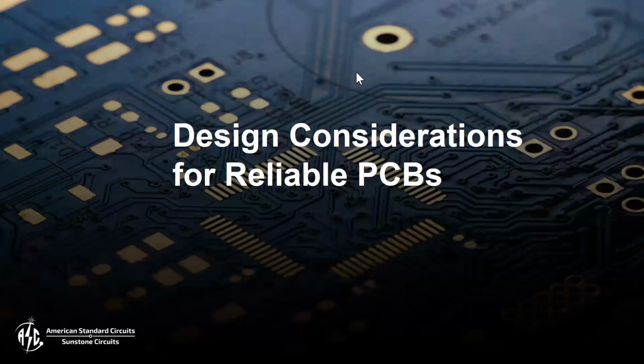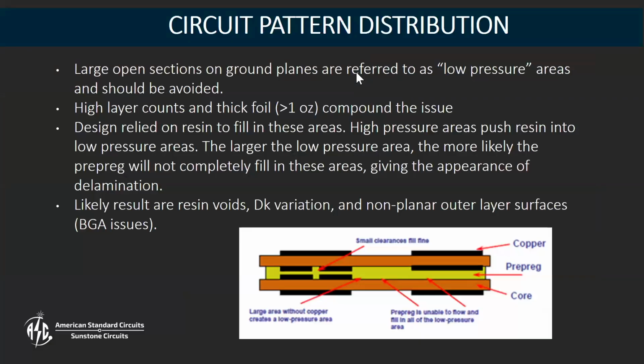All right, so design considerations for reliability. When you do your stack up in your design, there are a couple things to take into consideration with the planes and the layer to layer retained copper. If you have multiple layers, and usually this happens with higher layer count boards, sometimes it can happen on 4 and 6 layers, but usually it's in the higher layer count boards. Anytime you're either stacking copper in a specific area on every layer or eliminating copper on every layer in a specific area, it can create issues of either low pressure or high pressure during the lamination cycles.